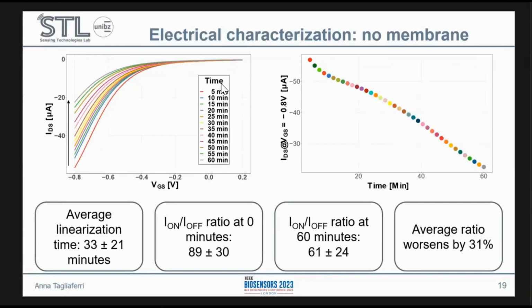Of course, it is not enough to just test the time. We also had to verify how the performance changes over time. And we calculated the on-off ratio, the ratio between the highest and the lowest current that we have measured. For this, the current decreases over the span of 1 hour from 89 to 61, with an average worsening of the performance of 31%.